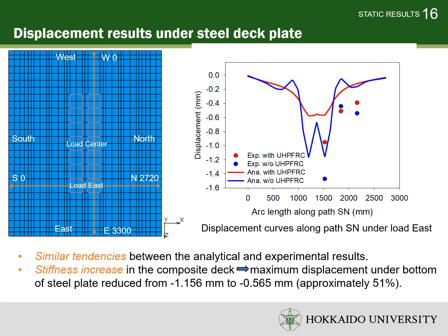From the displacement curves along both the path WE and path SN, it can be seen that the analytical results from the model with and without the overlay UHPFRC exhibit a similar tendency to the data from the experiment for both longitudinal and transverse direction. It was also found that the maximum deflection of the steel deck plates occurs under the east load.